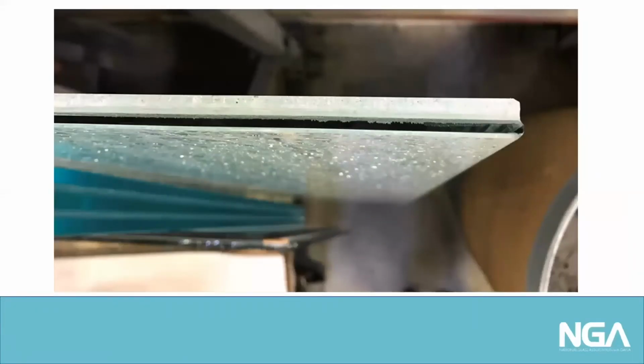Here's an example of a condition where it does show that increased fabrication, and a post-fabrication situation shows that in this particular case, they took a little bit too much off the edge, and it caused a fracture of one of the tempered plies on this particular piece of glass that was laminated and then post-finished with an undesirable result.